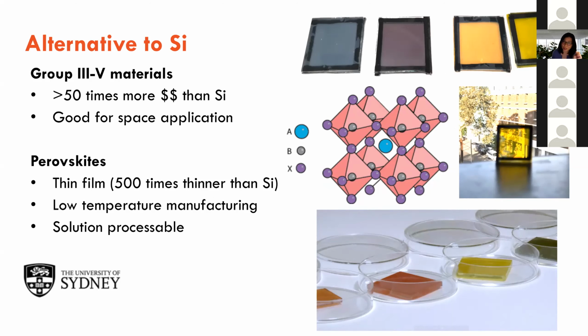So all these examples I show you are fabricated using the precursors of the materials dissolved in a solvent, and you can spread it, you can print it, you can spray it, you can even blow dry it onto the film. And you can also make it different colors by tuning the composition for the band gap. Materials with different band gaps will have different appearances as well.